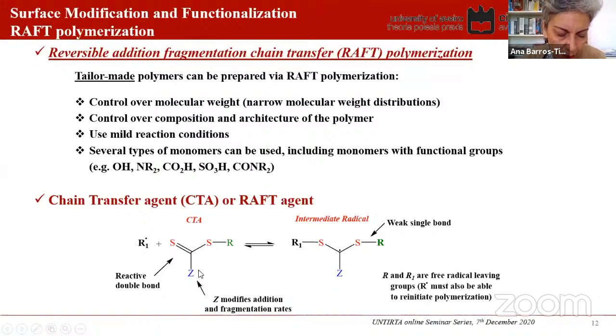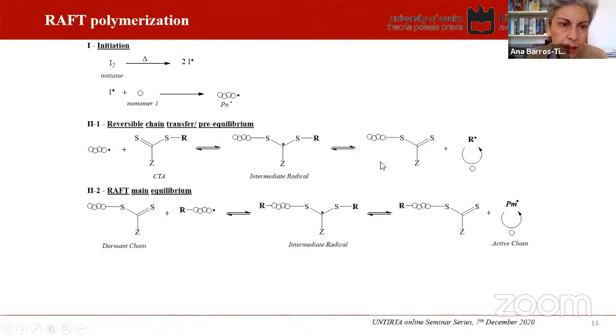where we have a leaving group which has a very weak link with the sulfur group, and is the one that will be broken and expelled so that the reaction can continue. And also has this Z group that modifies the addition and fragmentation rates during the polymerization. We start with a radical species, which comes from a typical polymerization initiator, and then we will establish a series of reactions that will allow this polymerization to be carried out in a controlled way.